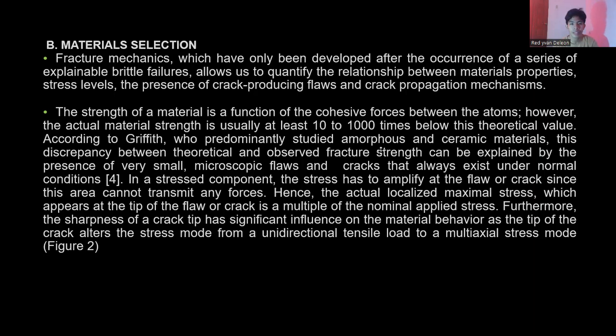The strength of a material is a function of forces between atoms. However, the actual material strength is usually at least 10 to 1,000 times below the theoretical value, according to Griffith, who predominantly studied amorphous and ceramic materials. This difference between theoretical and observed fracture strength can be explained by the presence of very small microscopic flaws.